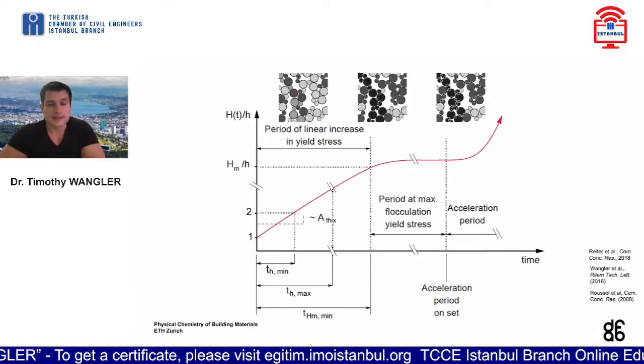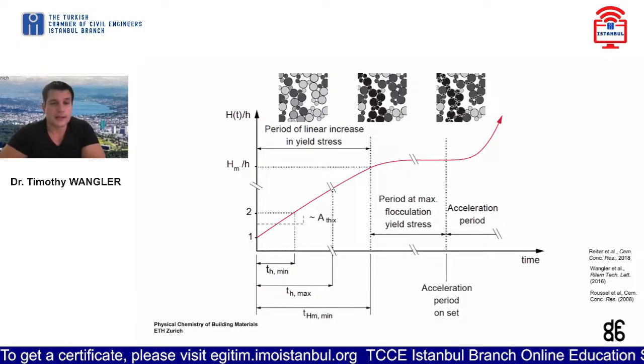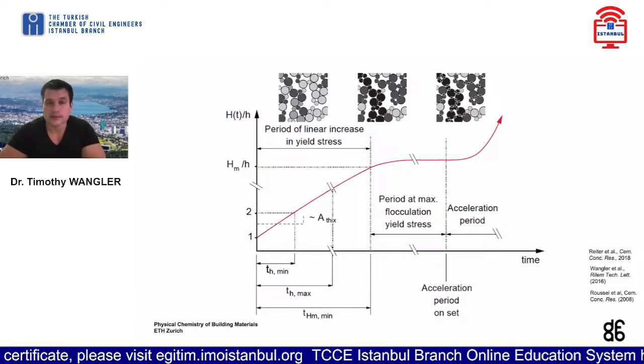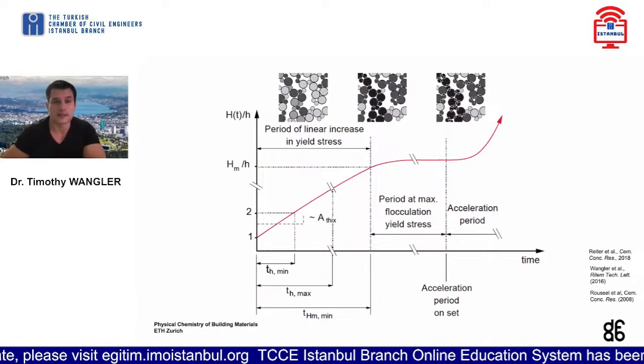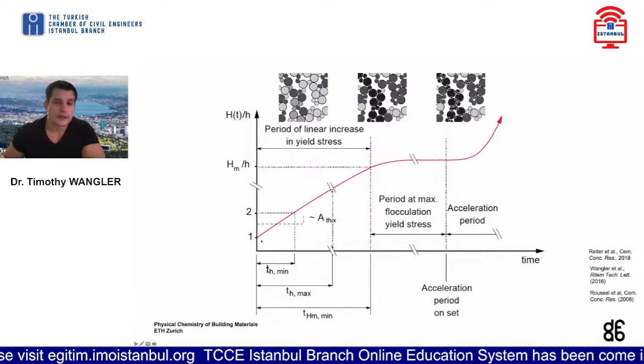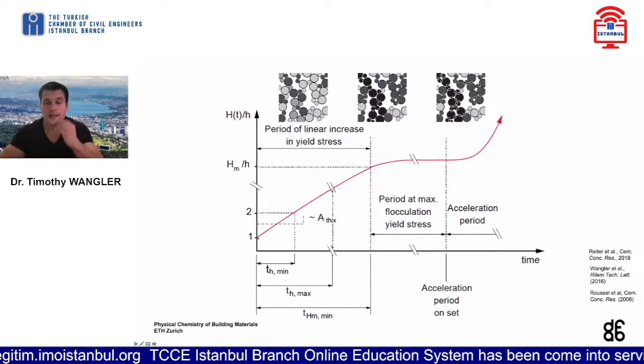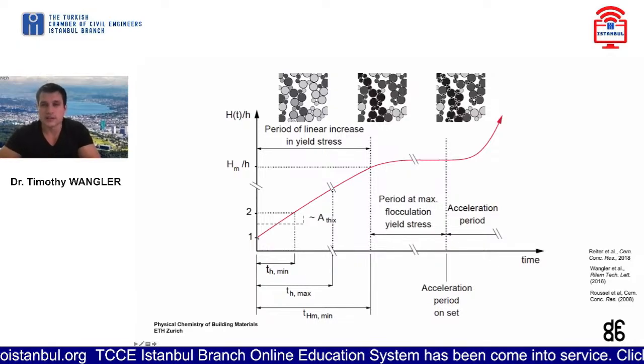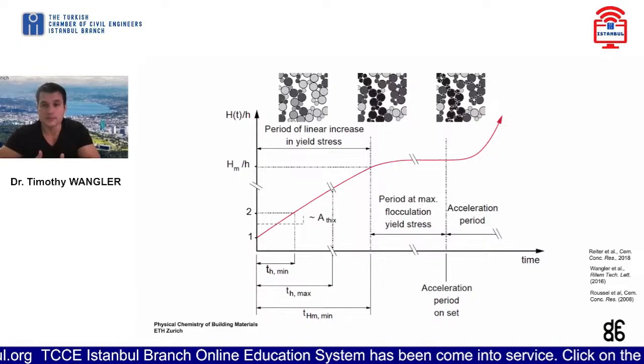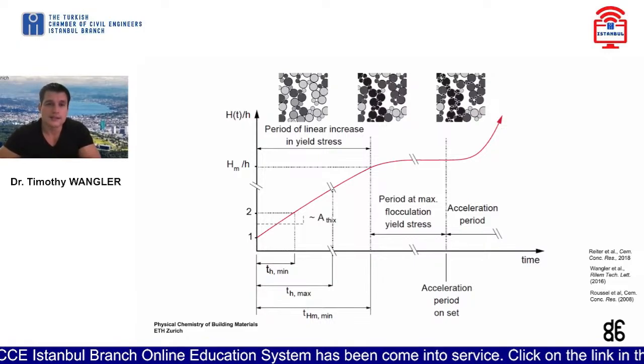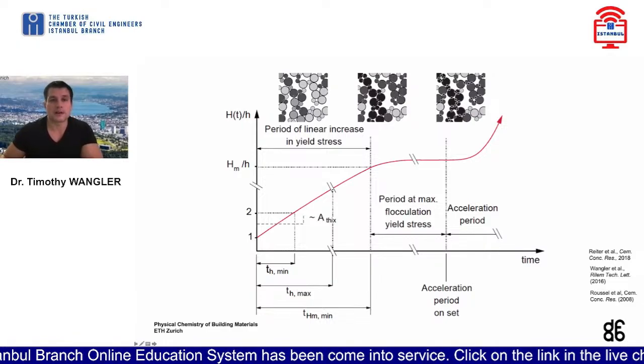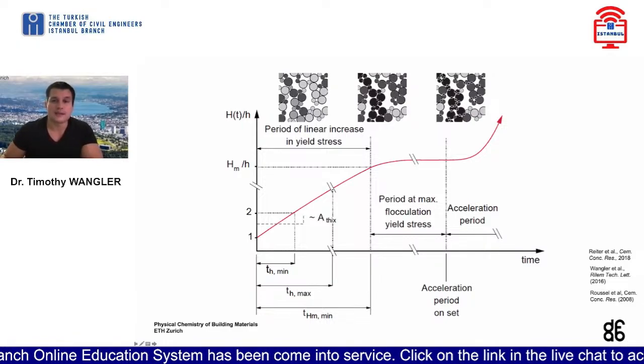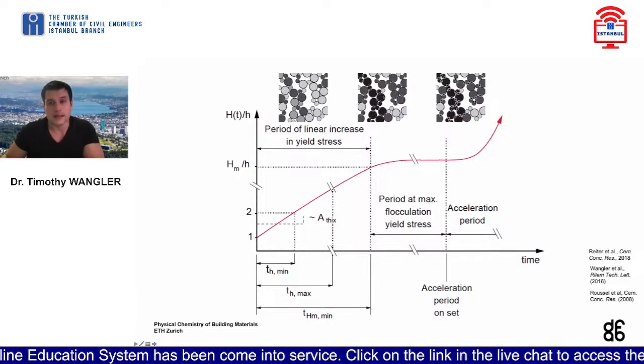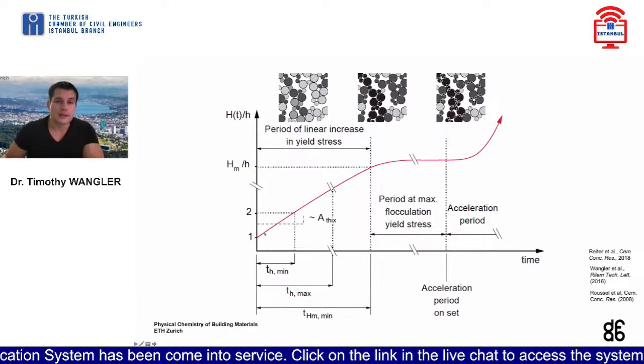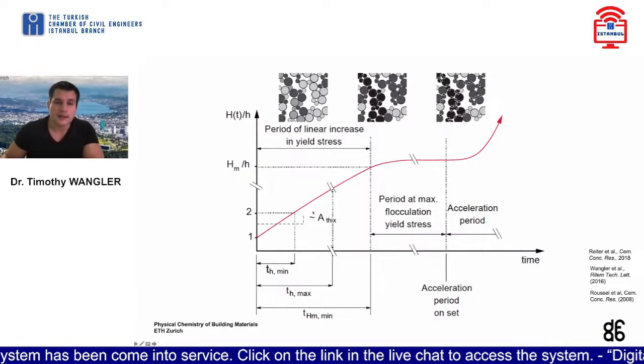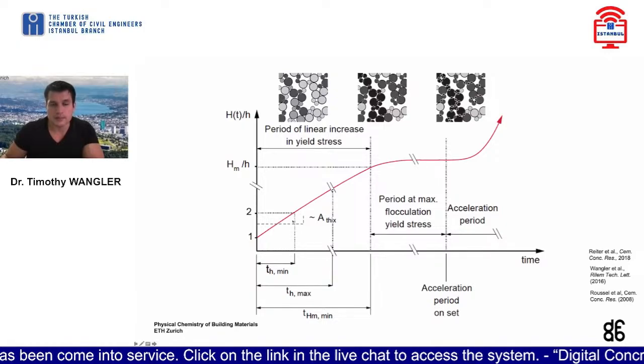And the reason for it is this. This graph gives you a concept of how strength builds up over time in a fresh cementitious material. First, there is some green strength, so it's fluid, and there is what is called normally in the field thixotropy. So some thixotropic buildup. Sometimes it's called a kind of green strength, and this is coming predominantly from flocculation processes between cement particles and some low-level hydration products being formed, but massive hydration hasn't started yet. And if you rely on this, the rate of this buildup is often called a thix.